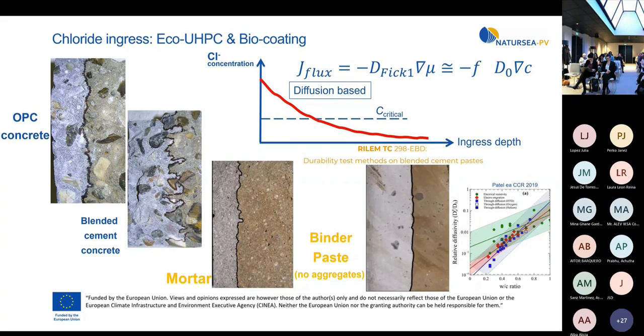You can see if you lower the water cement ratio, that means you have lower porosity. Basically, it goes from 100 to 1000, so 2 to 3 orders of magnitude, it lowers the diffusion process. But for UHPC, we are with very, very low water cement ratios, like 0.2. This explains why we have almost 2 orders of magnitude lower diffusivity than in normal concrete. That directly explains the durability.